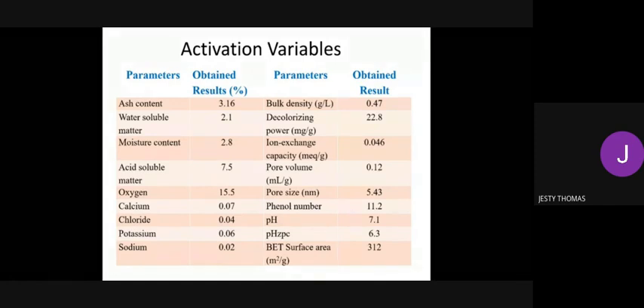After obtaining the particle size of 250 BSS, we put it through the activation variables to see whether these particles are suitable for the adsorption process. We looked at ash content, water soluble matters, moisture content, pore volume, bulk density, and BET surface area. I will discuss briefly. The water content is 2.1 and moisture content 2.8, which indicates that the compound is not hygroscopic in nature. The BET surface area was found to be 312 square meters per gram, which makes it a suitable adsorbent for the studies. All the parameters obtained were as per the quality standards mentioned by SNI 1995.